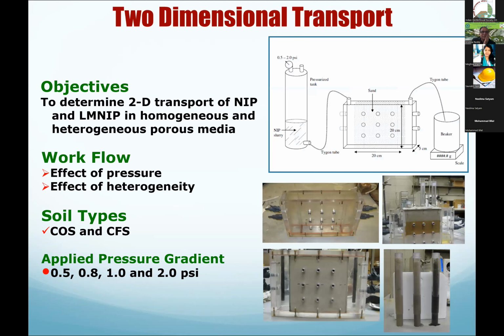For this one, we created this kind of experimental cell. It's like a tank. You will fill it with sand, and then you make a slurry of nano iron particles, modified or unmodified, and inject it into this chamber. Then you can pressurize it or allow gravity, and let it go through here, and you collect it on the other side, and look at how much volume is coming out, and you can analyze the contamination concentrations, or even the iron concentration.